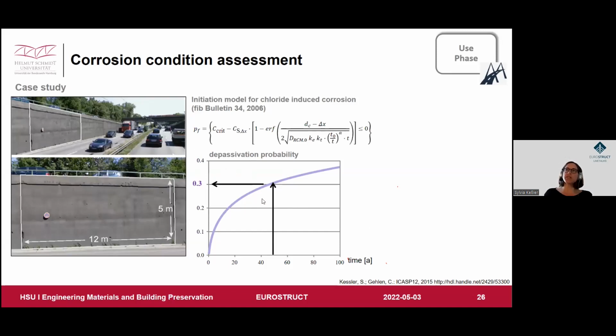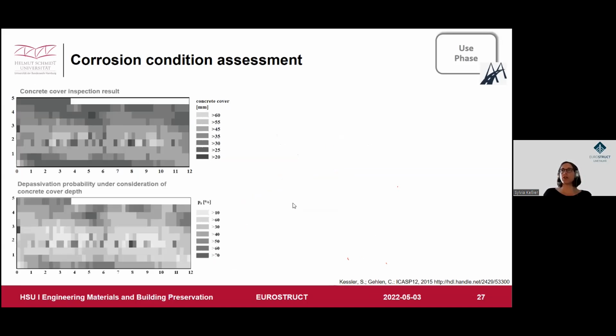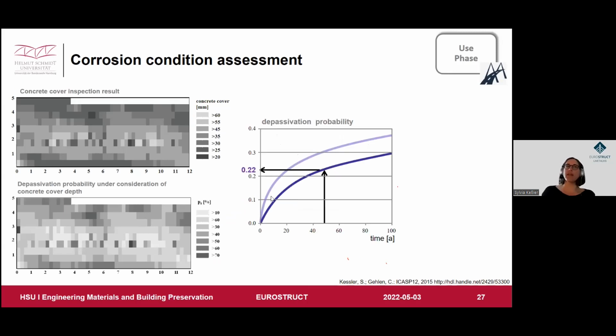Here are the results of the concrete cover. The concrete cover is slightly higher than you would expect, keeping in mind the design codes at the time of construction. And we recalculated the depassivation probability with the current concrete cover depth measurements. Now you see that the depassivation probability decreased because we have a much higher concrete cover depth than expected, and now we have a corrosion probability of 22%. Now you think, 22%, is it high, is it low? That is something you have to decide for yourself.